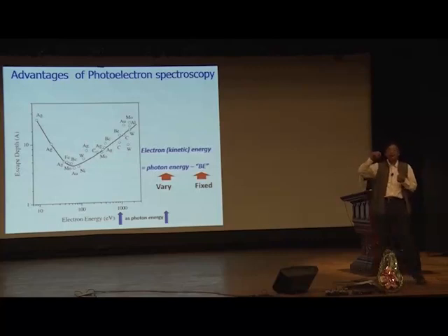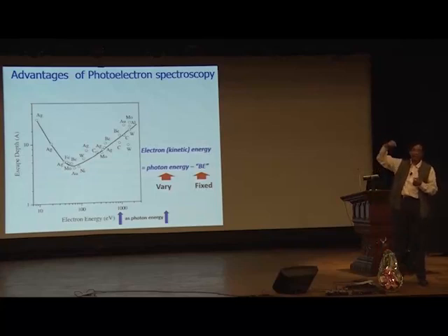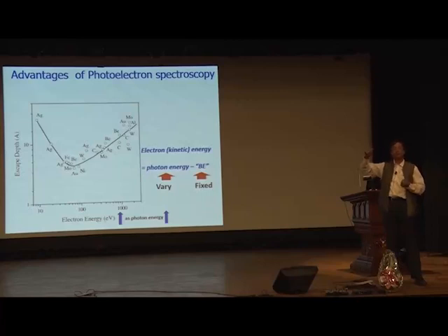So that is the average approximate thickness that I can probe with photoemission, right? So I come in with photons. Photons can go deep inside. It doesn't matter. The electrons only from lambda thickness, which is my inelastic mean free path, if it is generated within that much of the surface, and if it has the right orientation, it will come out of the surface, and I can measure that.